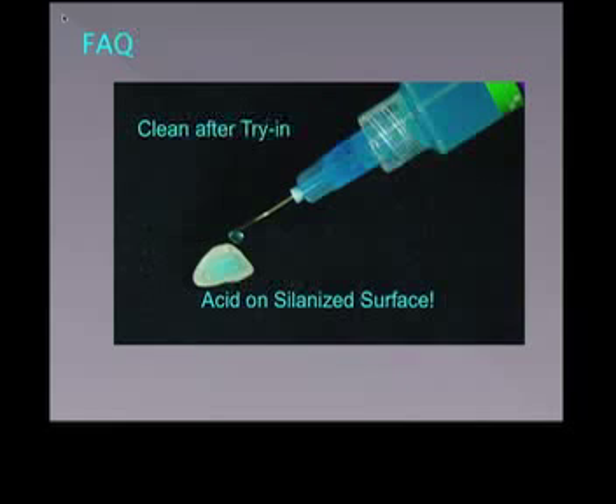Especially for veneers, the surface cleansing could be achieved with spherical glass powder sandblasting, but the porcelain bonding resin is HEMA-free, and this is a great product. It's a HEMA-free unfilled resin, making it a logical alternative to HEMA-containing hydrophilic resin. The placement of this porcelain bonding resin onto the surface allows for easier flow of the thicker resin luting cement and allows for confidence of flow into the tight proximal area of the seated restoration.